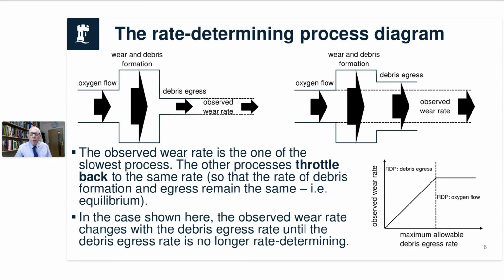But what we will see is if we push the debris egress up, so as I've gone from the left-hand side to the right-hand side, I've assumed that we've left parameters the same that won't change the oxygen flow, they won't change the wear and debris formation, but they might change the debris egress. For example, we now know that actually things like the fretting amplitude is probably one of the key ones that does this. Doesn't change the other things, but will change this quite significantly.